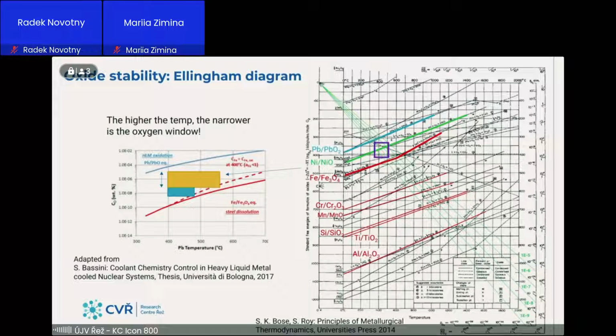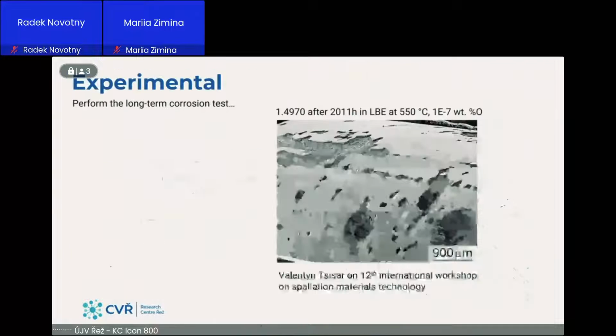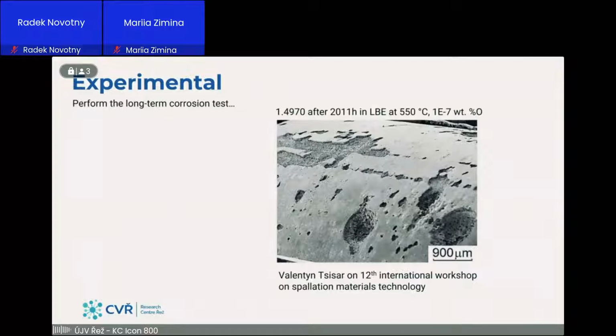Another fact is visible on this chart, that there is a problem if you increase the efficiency by increasing the outlet temperature. You are closing this window that's now pretty narrow. That means that it puts some stress on your oxygen control system. So that was some kind of brief introduction into the chemistry of liquid metal cooled reactors.